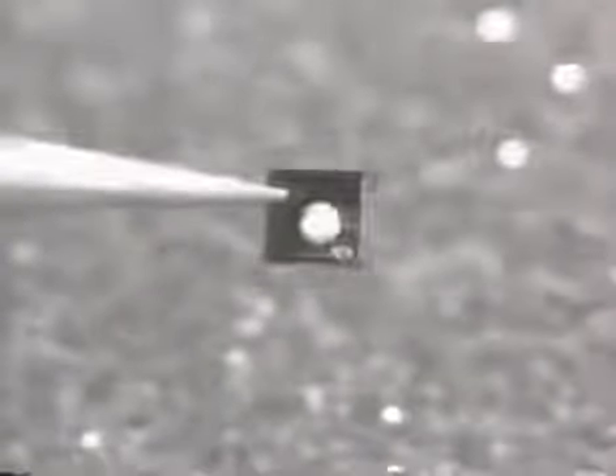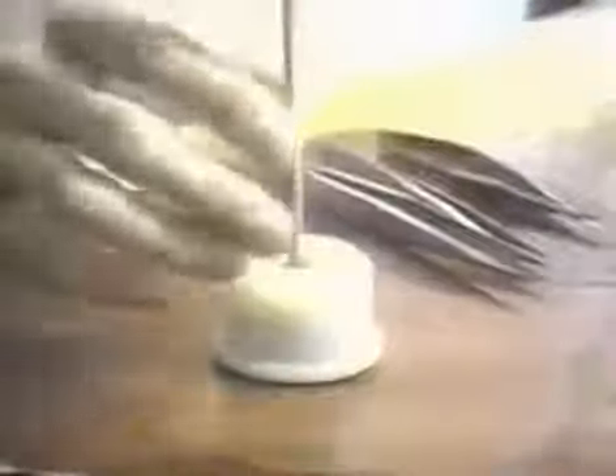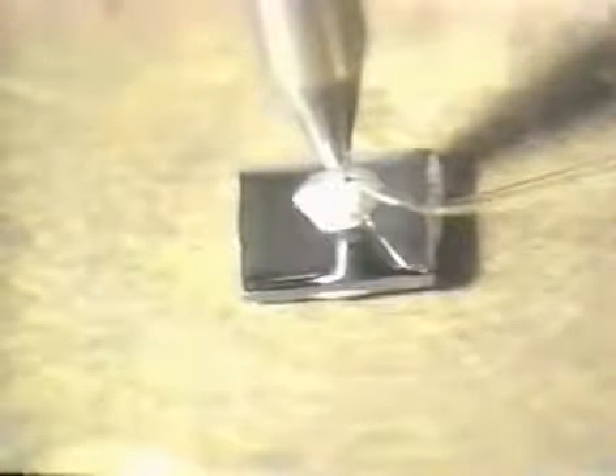We heat for 20 minutes at a temperature of 800 degrees centigrade. This finishes into an indium alloy that sandwiches the germanium. Gold wires are finally connected to the alloy portions to make electrodes. At the time in Japan, this was the main job of female factory workers called transistor girls. The job of connecting gold wires one by one while peeking through a microscope was work that required patience and dexterous fingertips.